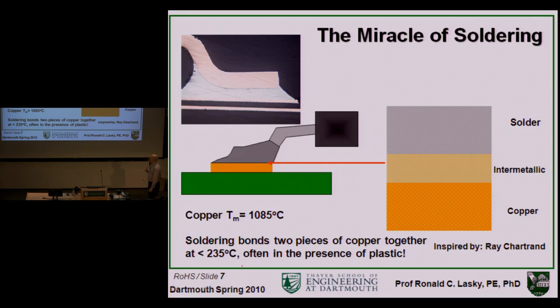And that is that what we're really doing when we assemble something in electronics is we're essentially bonding copper to copper. That's what we have to do. And if we didn't have solder, the melting temperature of copper is 1,085 degrees C. So soldering enables us to bond 2 pieces of copper together at less than about 235 degrees C, which is near the melting point of tin, tin being the base material for most solders.